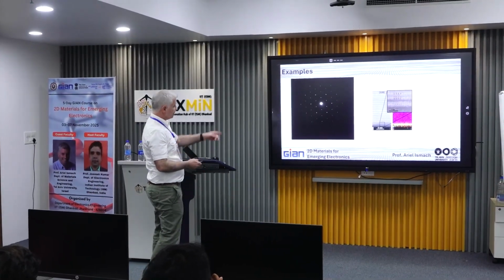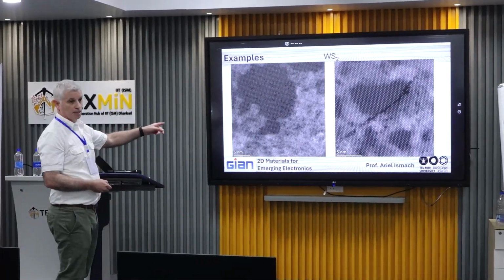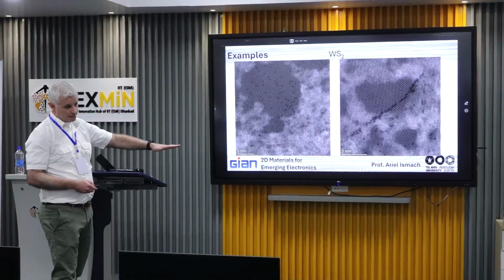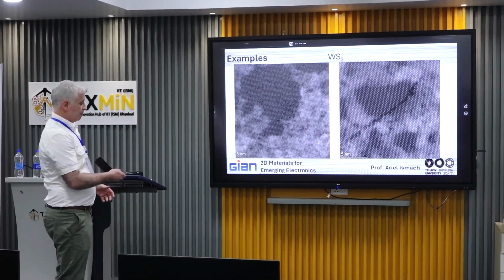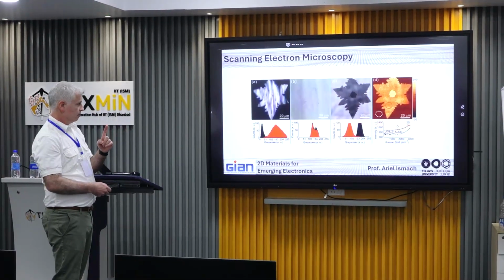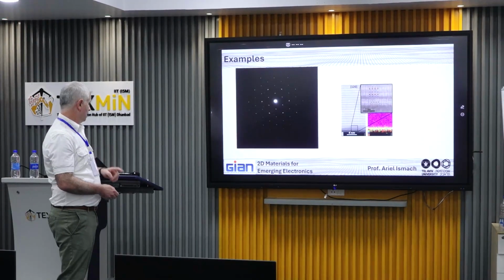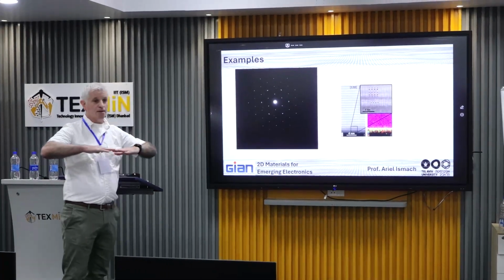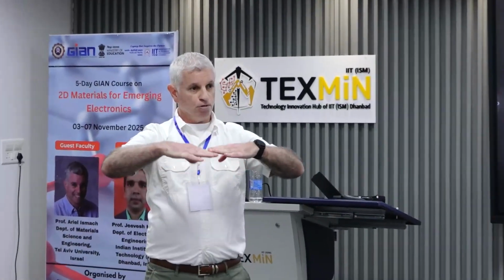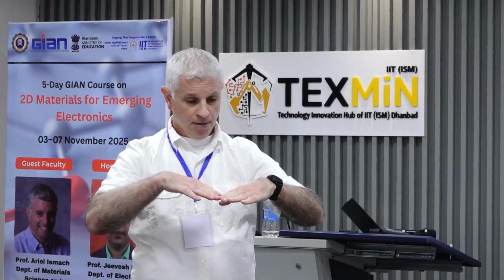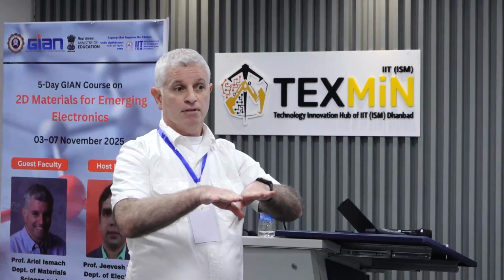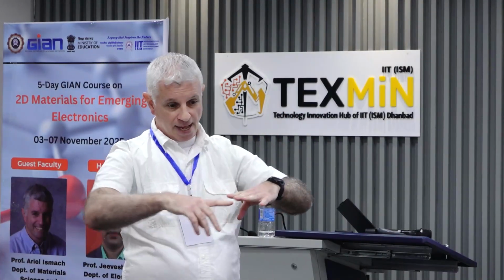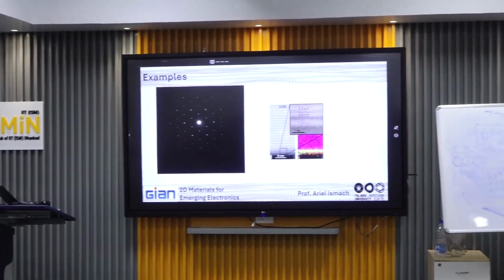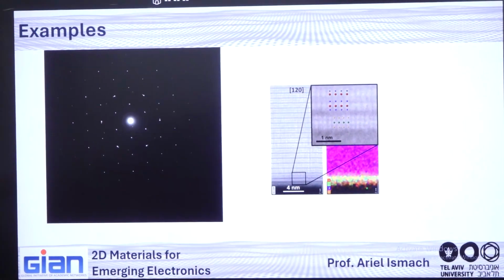So what you can see here is electron diffraction from this sample. You have a hexagonal lattice, single layer, single crystal in the area of the sample that gives you only one hexagonal pattern in the diffraction. Now, if you do the same diffraction in an area where you have domain boundaries, so you have 2, 3, 4 boundaries meeting together with different orientations, then you will see 3, 4 different hexagonal patterns which are rotated according to the relative angle of the lattices. So this is also a very good method to check twisted layers, to check exactly the angle, for example, of the layers.